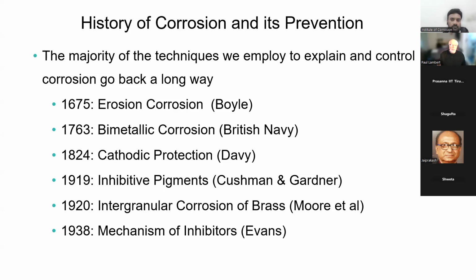Bimetallic corrosion actually is much older than you'd think. It dates right back to 1763. We'll have a quick look at that in a minute. Then we've got cathodic protection quite a bit later, because those two are sometimes linked much more closely than they truly are. We're looking at about 60 years before cathodic protection comes about. Cathodic protection is a consequence of an awareness of problems with bimetallic corrosion, but it isn't directly related to it. We get things like inhibitive pigments, not so much being made as understood.